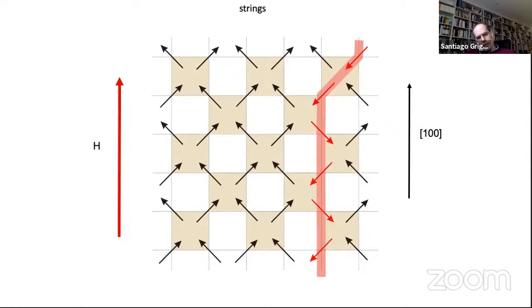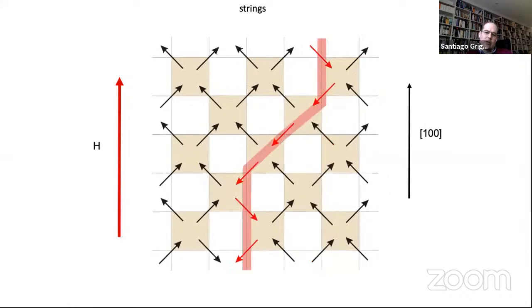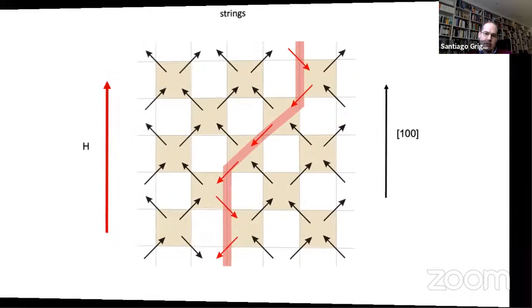But even in this limit, you can get some other type of excitations, and these excitations are these strings. You see that here, what I've done is I flipped a whole line of spins. So you see that now these red spins point down, but when you go to each tetrahedron, still you have that 2 of these spins are pointing in and 2 are pointing out. So for these excitations, you don't pay any energy in terms of J. So even if J is infinite, these excitations can still exist. And once you have them, of course, they're free to move. You see, I can move them, and I'm still obeying the Gauss rule on each tetrahedron.